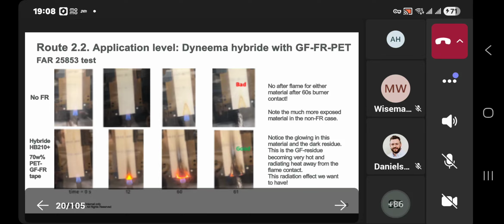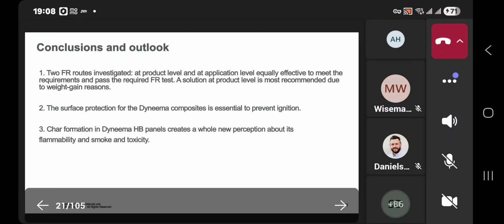So, next slide. Concluding, we explored two routes, one at product level and the other at application level, and both are very effective and meet the requirements to pass the relevant FR tests. We are recommending a solution at product level for weight gain reasons. We see that the surface protection of the Dyneema composites is essential to prevent ignition, and if ignition doesn't happen, the material won't burn. And we are convinced that char formation in Dyneema consolidated panels will create a whole new perception and change the perception that is out there about its flammability, smoke, and toxicity. That's it. Thank you.